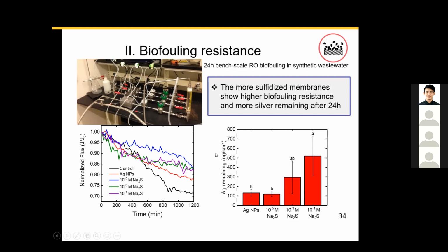Not only that, but when we took the membrane out of the module and tested how much silver was remaining on the membrane surface, we saw that for the silver nanoparticles, a lot of the silver was depleted. But upon sulfidation, the thicker the layer of silver sulfide, the more silver still remains on the membrane surface, which can help us improve the lifetime of these reverse osmosis membranes.